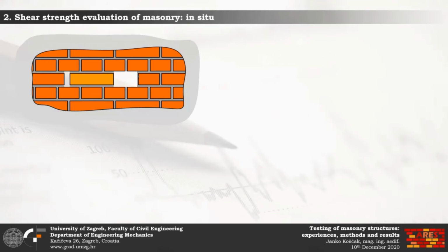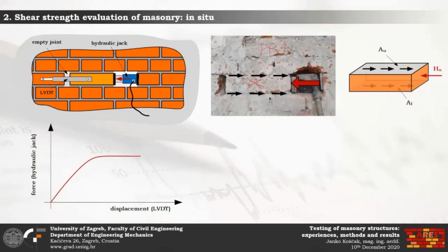The test is performed on a longitudinally oriented brick, as shown in the figure, and the joints with some additional space on both sides of the tested brick should be cleared for the insertion of the hydraulic jack. This also needs to ensure that the brick is not restrained on the opposite side of the hydraulic jack, and additionally, brick translation during the test can be measured with an LVDT sensor. Okay, the pressure of the hydraulic jack should now be increased until the maximum value of force is attained. Right now, the brick is sliding along its horizontal joints without, of course, pressure growth.